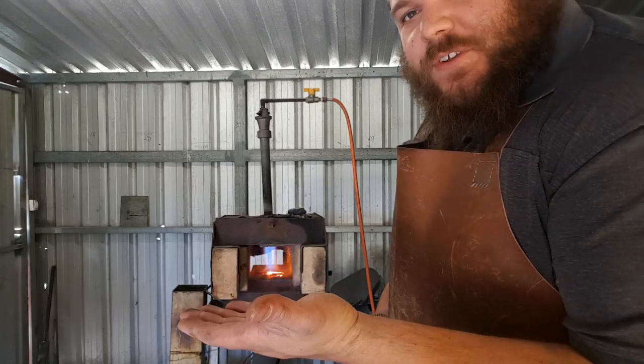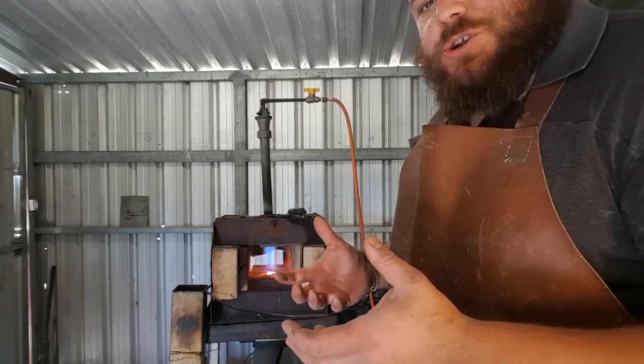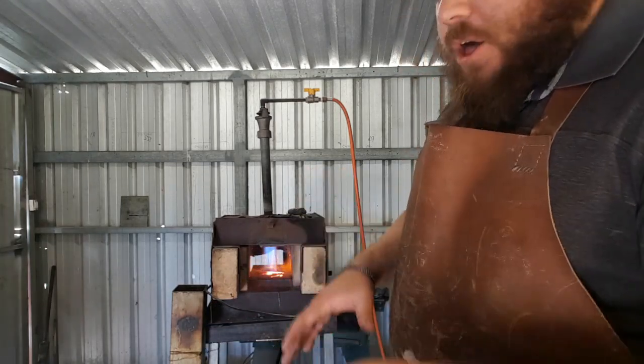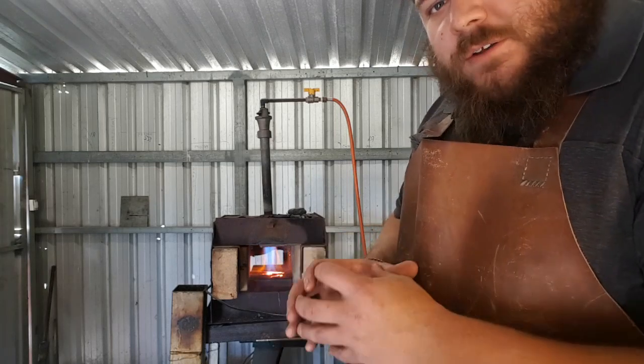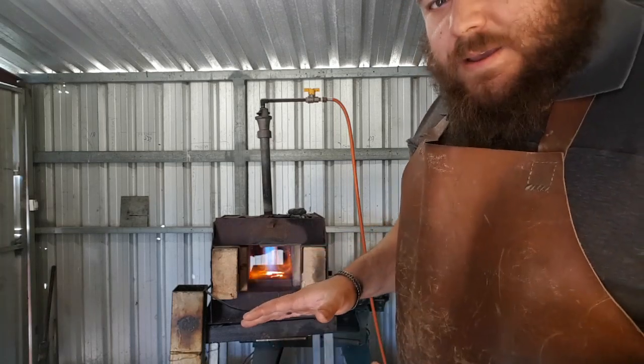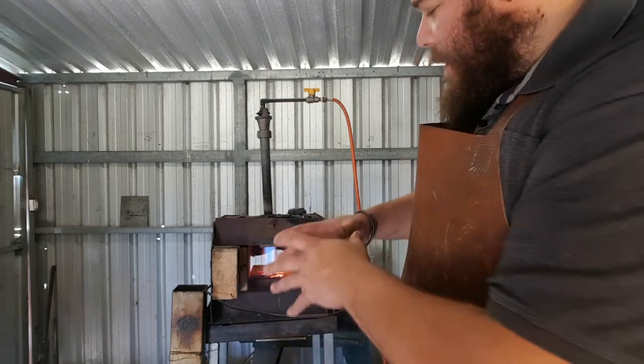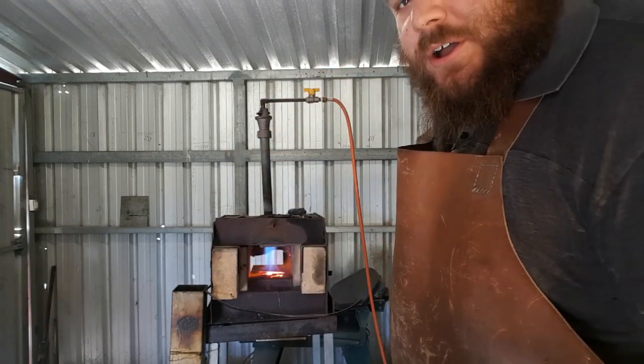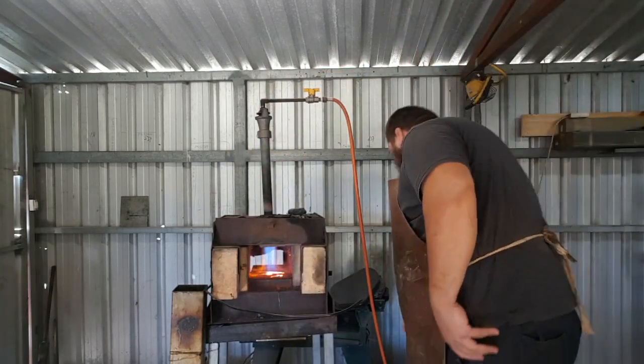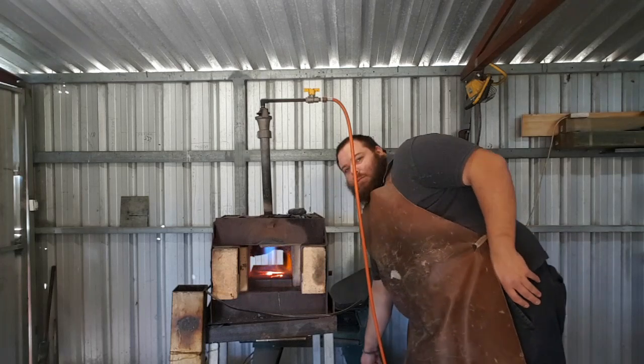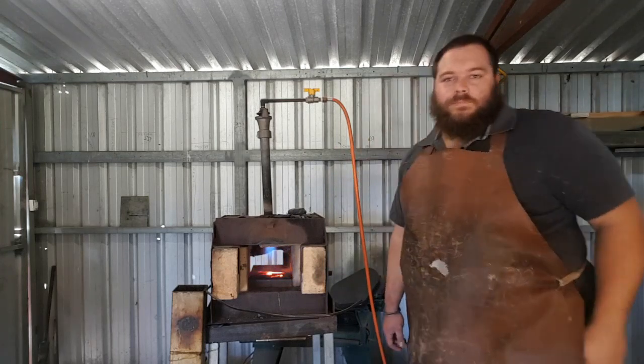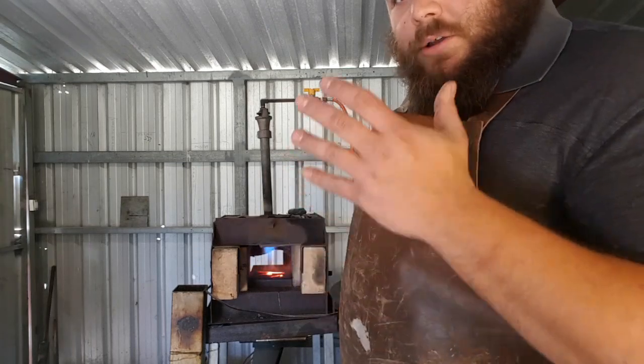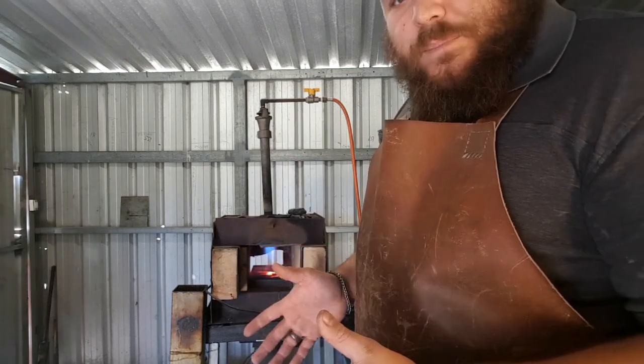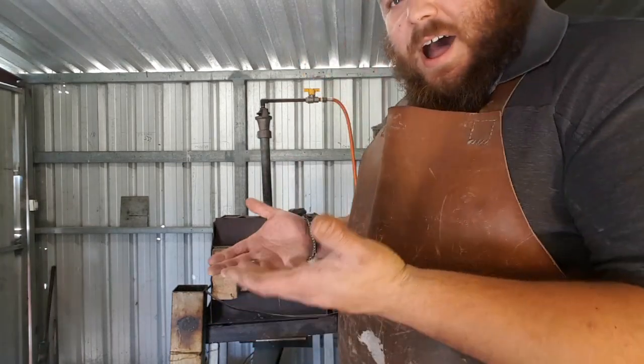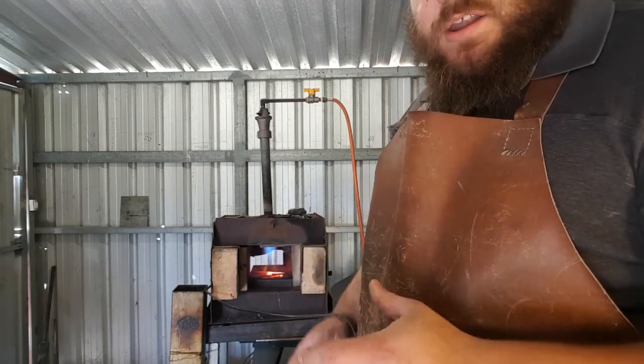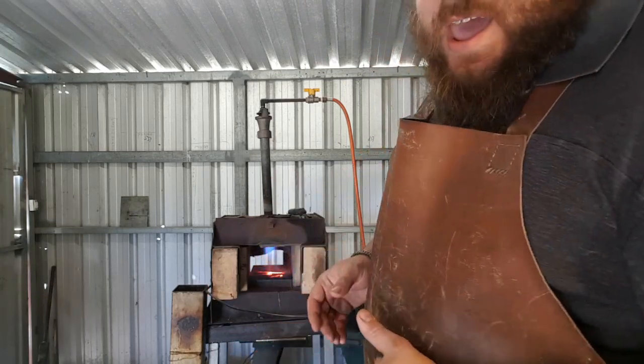Touching the bottom of the forge floor, that is the highest temperature I can run. If I go beyond that and I start creating a cold spot on the floor, I'm basically just wasting energy to the outside of the forge. So, turned it back down to 15 to 12 psi, running that about half width flame. That's going to give me a nice neutral atmosphere when I shut off the air.